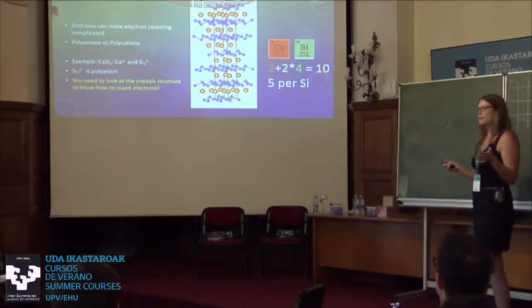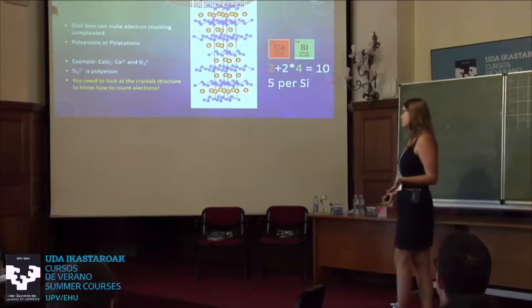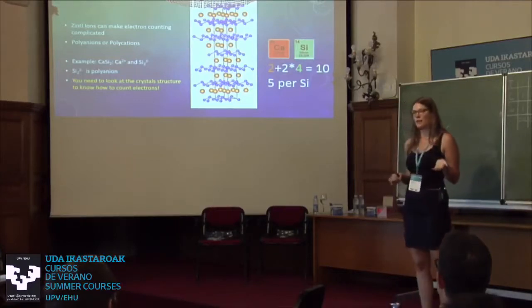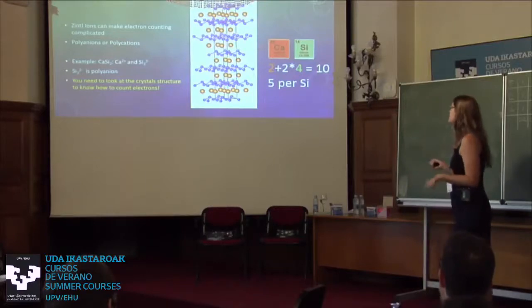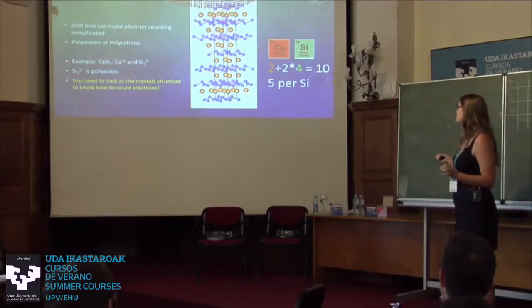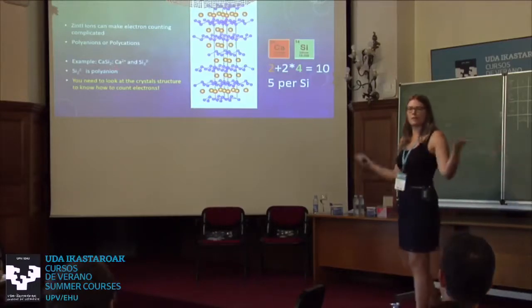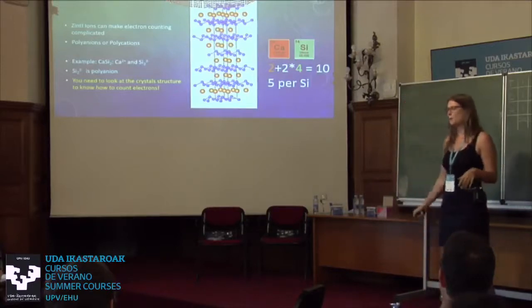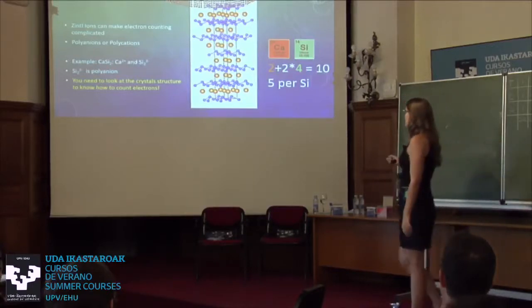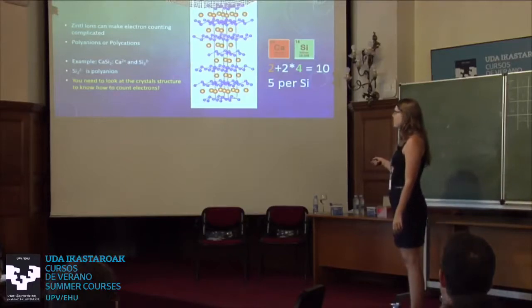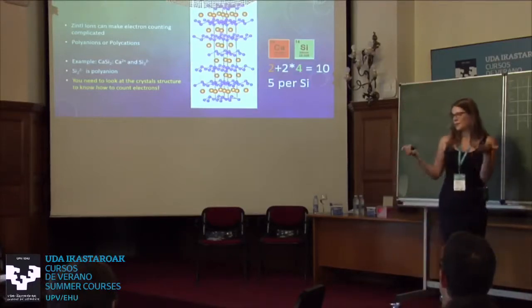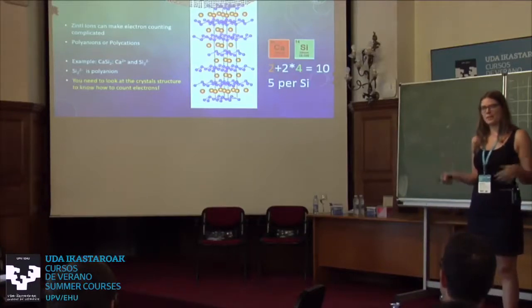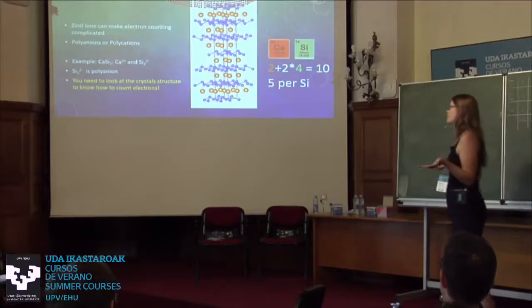So Zintl phases are phases which are semiconducting, but they don't appear so if you just look at the electron count. A very famous example is this calcium silicide here, which is a semiconductor, but if you would count the electrons, you would count 10, and even if you divide it by 2, because there's CaSi2, you would count 5 electrons per silicon. This is nothing charge balanced, right? You think it has a half-filled p-band. However, when you look at the structure, you can see that each silicon is bonded to 3 other silicons. So each silicon is sharing electrons with the other ones, and then the electron count matches again. Okay, and we have a charge balanced compound.